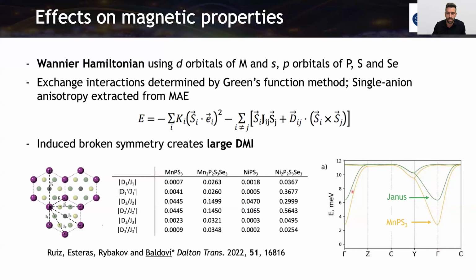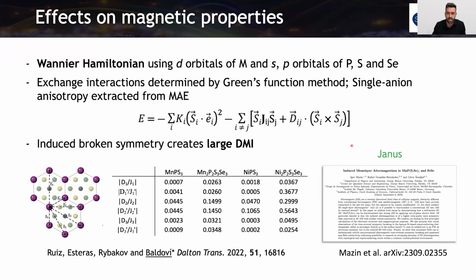This is the magnon dispersion in the case of the manganese. And we can observe here that from the manganese PS3 to the Janus, there's a clear effect of this anisotropy. I recommend reading this recent work by Mazin et al.. It's now on arXiv, where they are modeling and looking at the possibilities of making this material a possible alternative.